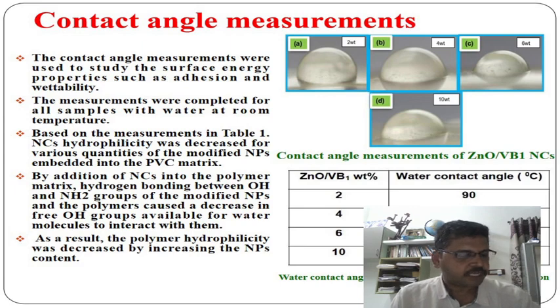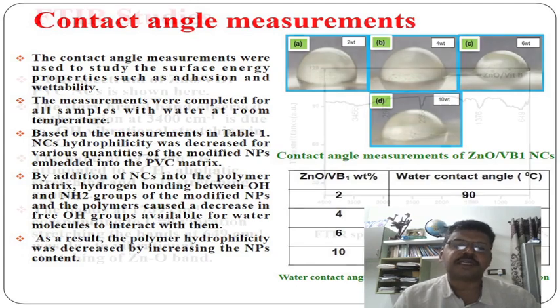the nanoparticles. The hydrophilic properties come from the existence of hydroxyl groups in the PVC chain. On the other hand, PVC has various OH and CO groups in its structure. It caused its good hydrophilicity as well as solubility in water. By addition of NCs into the polymer matrix, hydrogen bonding between OH and NH2 groups of modified NPs and polymer causes a decrease in free OH groups availability for the water to interact with them. As a result, the polymer hydrophilicity was decreased with increasing nanoparticle content. So that is the contact angle measurements.